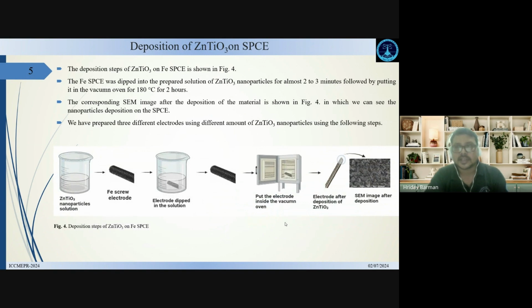After the synthesis of the material, we deposited it on the screen-printed carbon electrode, which we are going to use for the voltammetric analysis of water splitting. As we can see in figure 4, the deposition steps of the zinc titanate material on the SPCE have been shown. First we made a solution of zinc titanate material. Then we dipped the electrode in the solution for about 2 to 3 minutes, followed by putting it in the vacuum oven at 180 degrees centigrade for 2 hours.